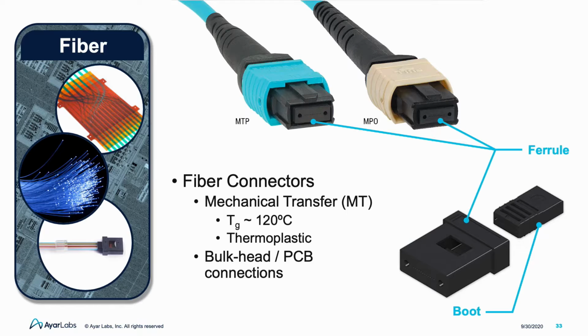Fiber connectors are another area of potential development. Fiber connectors are a high-performance and well-developed technology. However, they were developed for a central office environment. Let's start with the fiber ferrule, called a mechanical transfer or MT ferrule. It's typically fabricated from a thermoplastic. Currently, the glass transition temperature of this material is around 120 degrees C, which could result in stress relaxation, in other words creep, during the reflow process. Different material formulations or types can improve the thermal stability of these assemblies. Additionally, as the number of optical waveguides going to and from the MCP increases, we will need higher density ferrule technology.